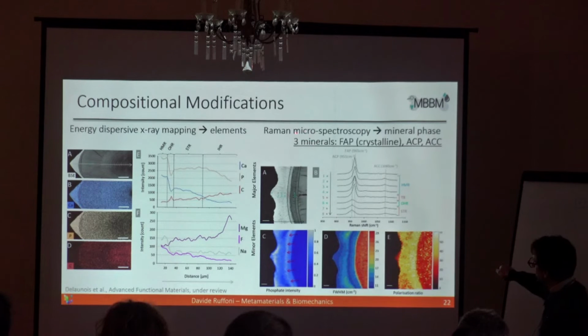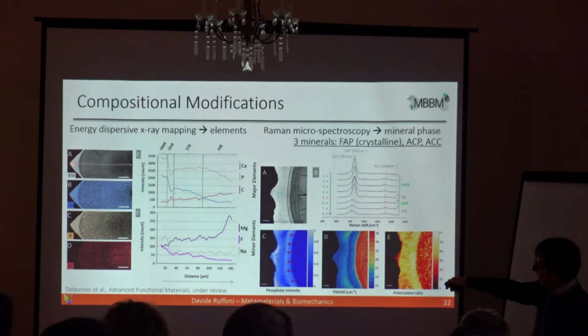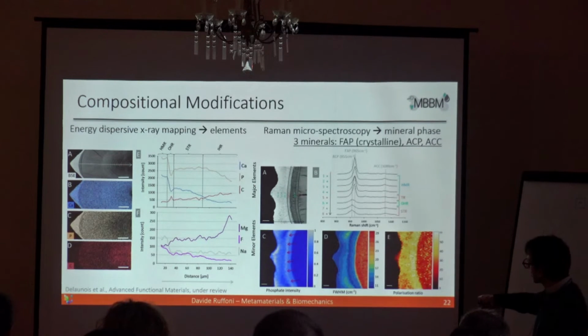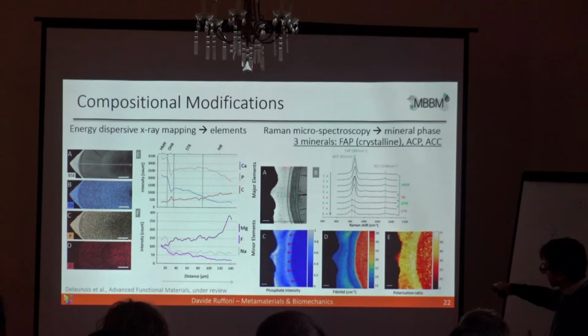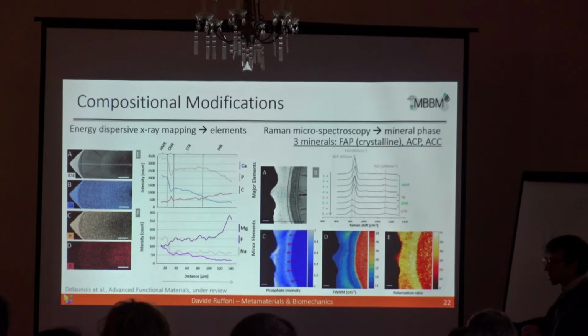And if we look with Raman microspectroscopy, so we exploited the Raman effect to see a little bit the mineral phases. Things that appear homogeneous under electron microscopy and energy dispersive X-ray mapping, so things that appear homogeneous in terms of chemical composition, are not homogeneous in terms of mineral phases. And actually we see 3 mineral phases reinforcing this structure. So we see fluoroapatite, which is a crystalline mineral. We see amorphous calcium phosphate and amorphous calcium carbonate. These 2 are common. Fluoroapatite is unusual, and fluoroapatite is harder and is also less water soluble than the other 2 minerals. So this is already a modification happening here at the surface to make this impact resistant.